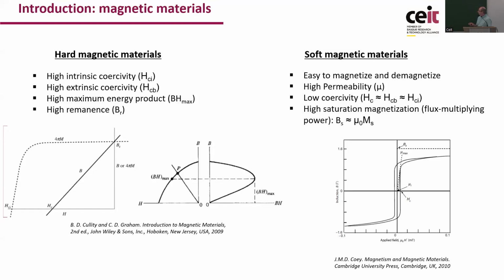In the case of the soft magnetic materials, the main characteristic that they must exhibit in application is that they are easy to magnetize and demagnetize, consuming very low energy. In order to do so, as mentioned before, the curve must be very narrow. That means that they must have a very low coercivity. If possible, the permeability must be as high as possible, because this is related with the velocity at which the material can respond during magnetization and demagnetization. And finally, another important property is the saturation magnetization, or the saturation magnetic induction field, which is an indication of the amplifying power of the external field that you are applying in operation.